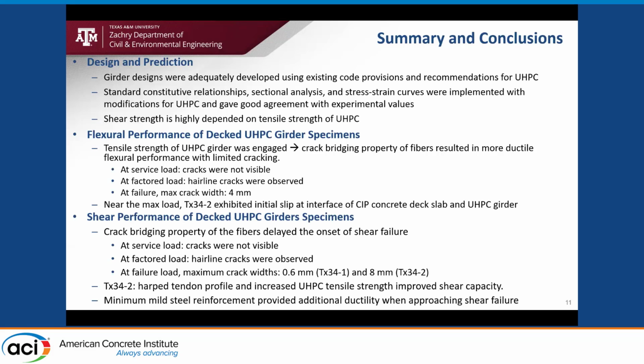The shear performance of these girders also showed great potential for reducing the minimum web reinforcement in these girders, and that would in fact make the design more efficient in terms of time and money. The crack bridging properties of the fibers tend to delay the onset of a shear failure. Cracking again was not visible during the service conditions, and beyond factored loading, we had more cracks being observed. Major conclusion that we drew is that increase in tensile strength, harping of strands, and higher prestressing force tends to largely improve the shear capacity of the girders even without minimum web reinforcement. Having minimum steel in the shear region will definitely enhance the ductility of the specimens.